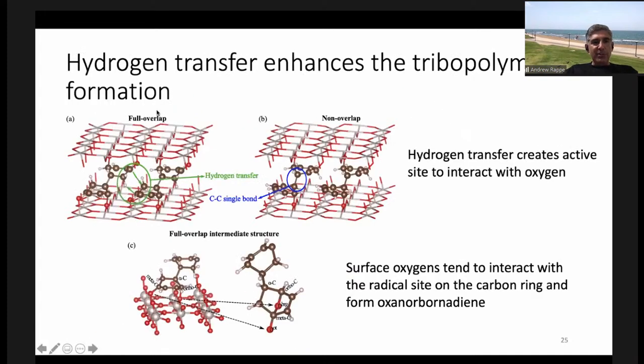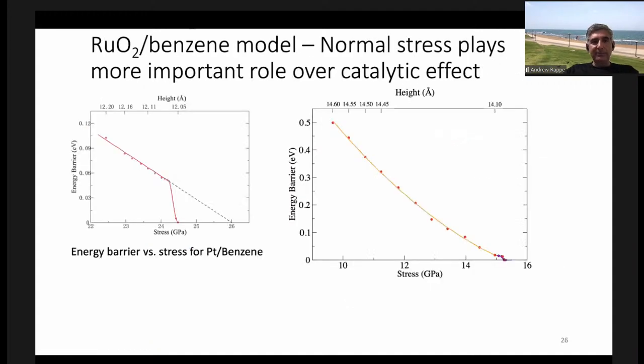Okay, so here's a zoom in of this. This is the full overlap case, which gives you the reaction. So there's a hydrogen transfer, and then a carbon-carbon single bond is formed between one ring and the other. But when it pulls away, it takes two oxygens with it. And if you look closely here, this oxygen bridges across the center of what was the benzene ring, and then this oxygen bonds to one carbon. And so this kind of six-membered ring with a bridge is referred to as an oxa-norbornadiene. And so that's an interesting formation of an oxygenated species through this tribochemical reaction.